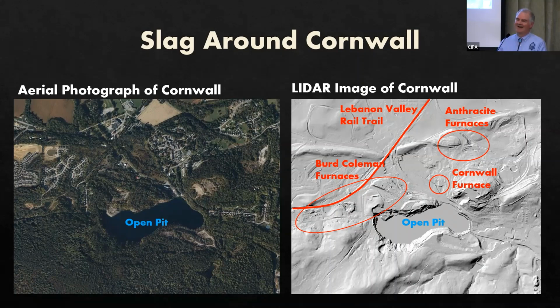I was wondering if you had a product that would mix slag in iron. Oh, yes. So the question is, is there a product where there's mixed slag and iron? Some of our samples that we have up here have iron mixed in with the slag, so you can see that. I'm not aware of any intentional mixing of slag and iron as a product, but I am aware that for many years, slag piles were mined to recover the iron that escaped in the slag. And it was actually a good way to feed a furnace because the iron had already melted and it had been somewhat purified, so it was a good source of iron.